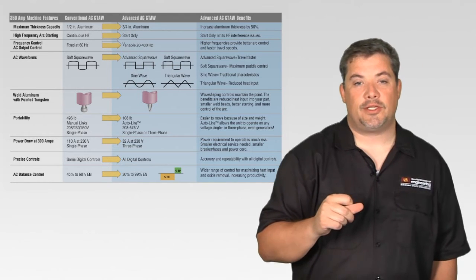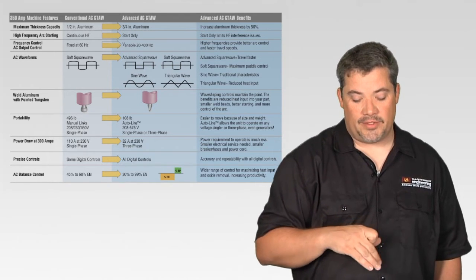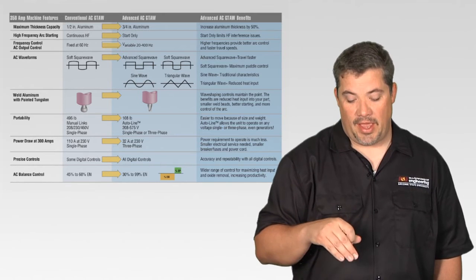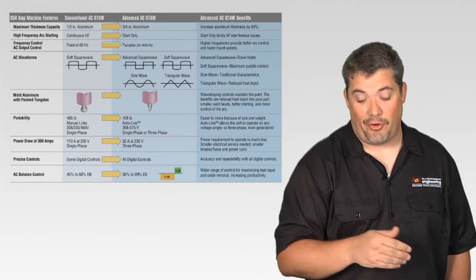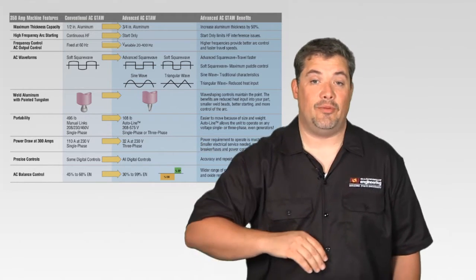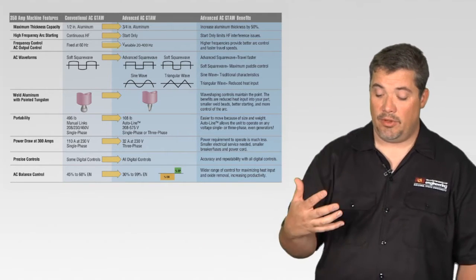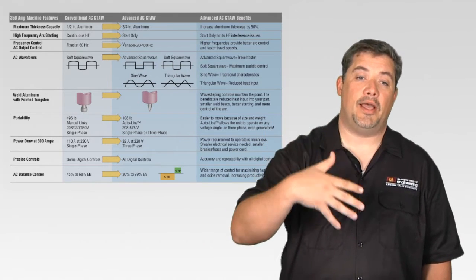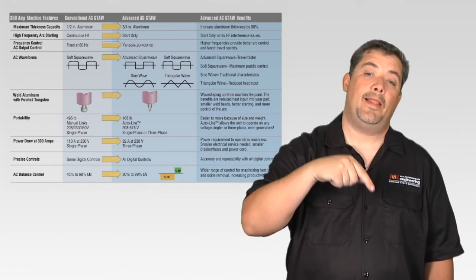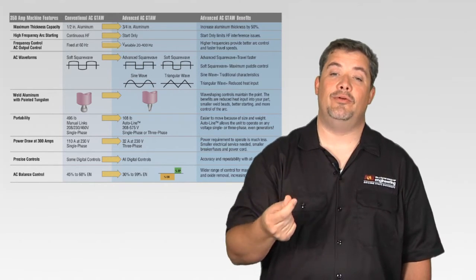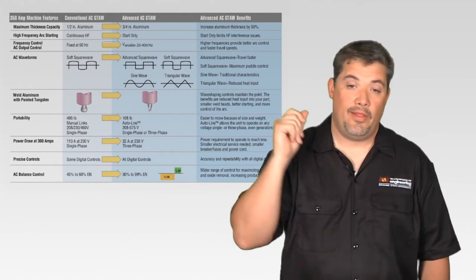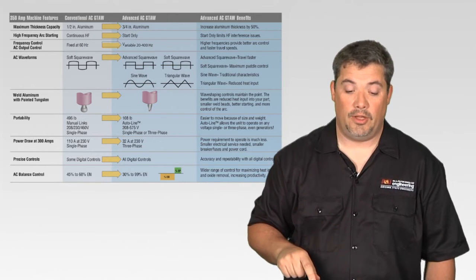Then we have AC balance control. 45 to 68% electrode negative, and on the new machines I can go from 30 to 99% electrode negative, so much bigger range to really balance and optimize how much heat we're putting into the part and minimize how much etching we need to do, because etching just gets that oxide out. The rest is helping me weld a little bit more efficiently.